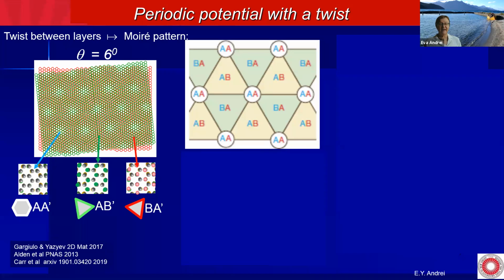And when you do an STM topography, you only see the atoms that have no partners in the bottom layer. So instead of seeing a honeycomb structure, you're going to see a triangular structure like this. Now, if you go to the other side, we have BA, where the opposite happens, and it's the A atom in the top layer that has no neighbor, so the triangle turns to the right. And here you see how this looks. You have the AA region surrounded by alternating AB and BA that are separated by a domain wall.